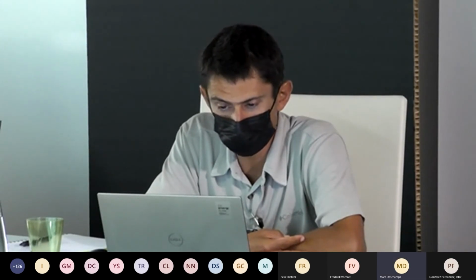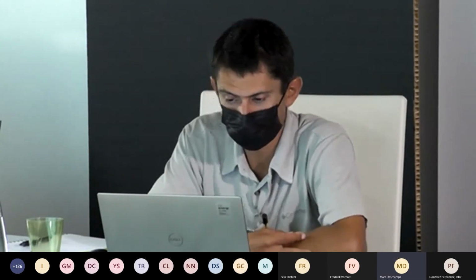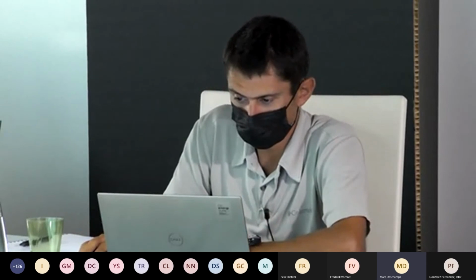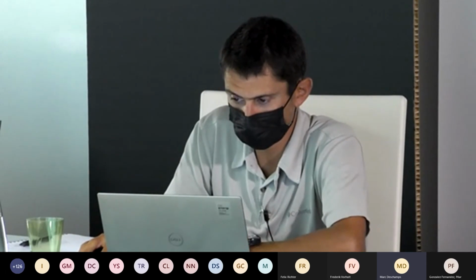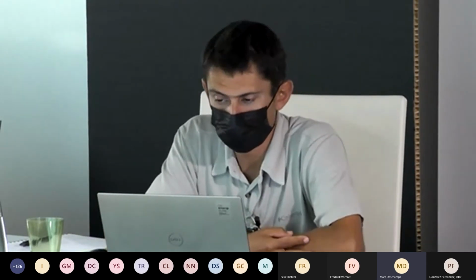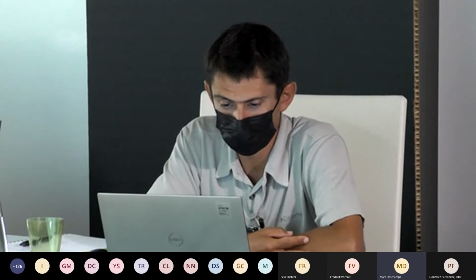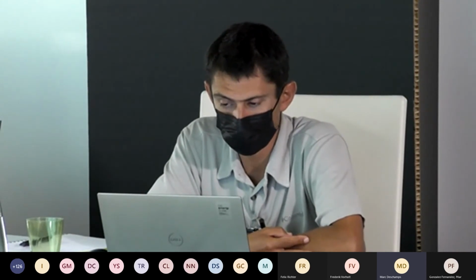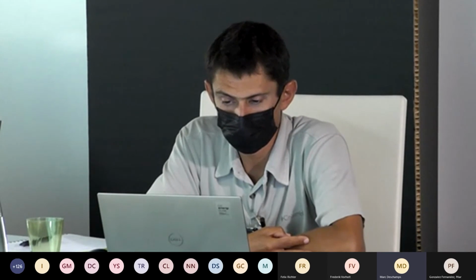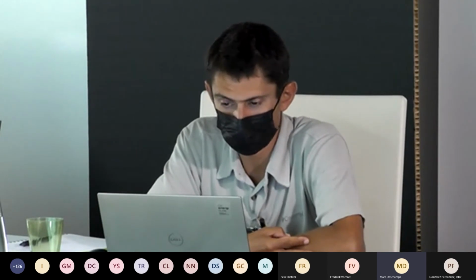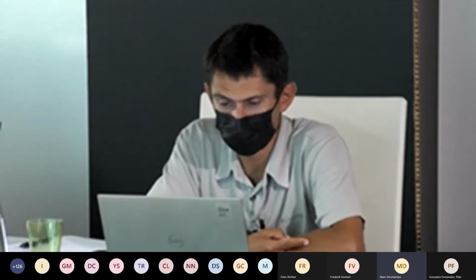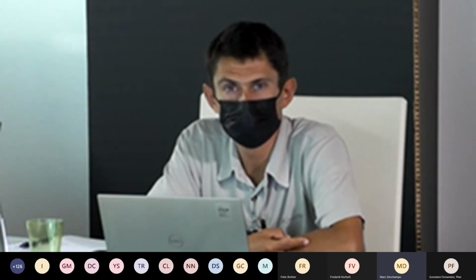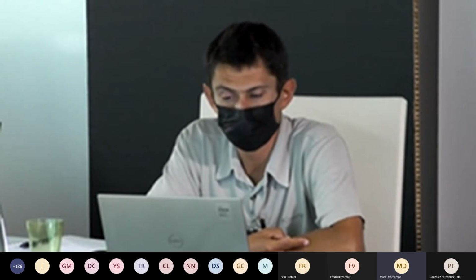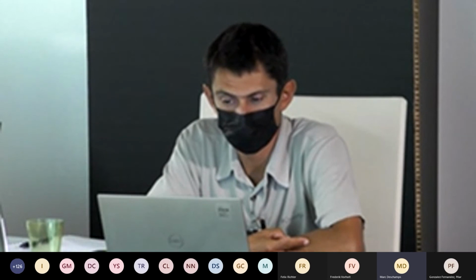We are playing on two sides. One side is the interface between lithium and electrolyte. Having a good interface is very important. You can play with different parameters to have that, but I will not give you the right one. And the other one is the electrolyte. We have designed a special electrolyte to avoid dendrites. So it's the combination of interface and electrolyte to reach that point.